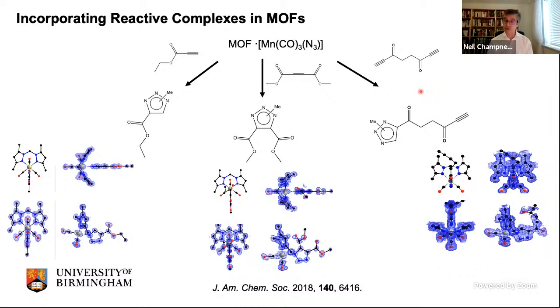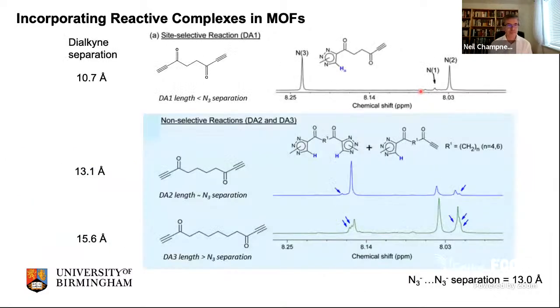And this happens because of the MOF structure. So if we take dialkynes of different lengths, then we can actually look at this process. So in the crystal structure, the azides are separated by 13 angstroms. So if you take a dialkyne which is shorter than that, so this one is 10.7 angstroms, then it only reacts at one end. And we desymmetrize the dialkyne and we make a triazole alkyne species.